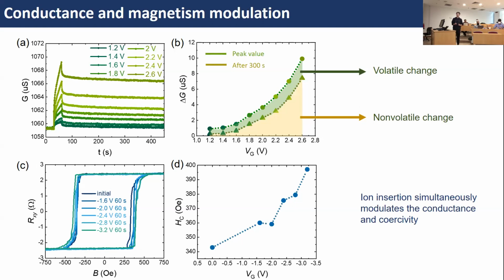Then, to find out the response of these films to different external stimuli, we apply gate voltages of different amplitudes from 1.2 volts to 2.6 volts. And here we can find that there is a peak, and then it gradually decays and stabilizes at a certain value. Here we define the peak value as the volatile change of the resistance, while the stabilized value at 300 seconds is the non-volatile change. It means that the volatile change is the short-term plasticity, while the long-term plasticity is the non-volatile change.